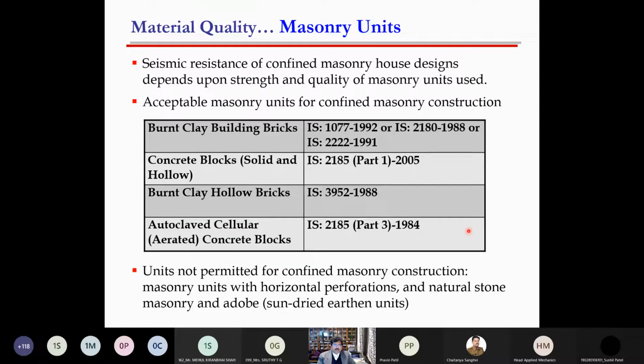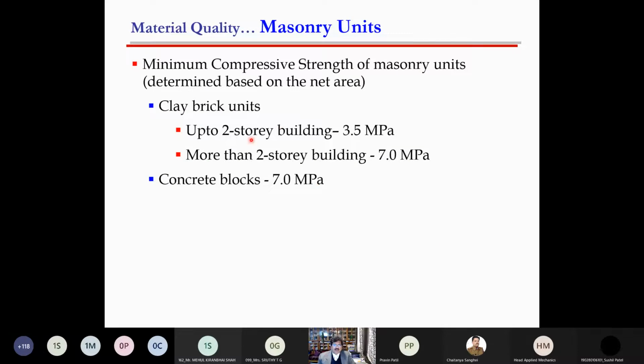So I will try to show you some of the important parts of this code, and where you can engineer your confined masonry, not just follow the prescriptive approach. It says you can use any kind of masonry unit: burnt clay, even the fly ash bricks, as I showed you, or even AAC, but you need sufficient strength. That comes from your calculations. For up to a 2-story building, you should have 3.5 MPa. For more than 2 stories, you need 7 MPa, and concrete blocks should be more than 7 MPa. If you're using AAC, make sure that it is 3.5 or 4 MPa.